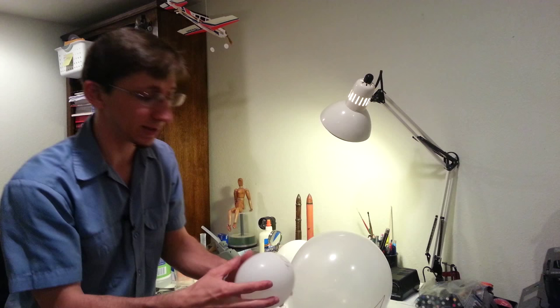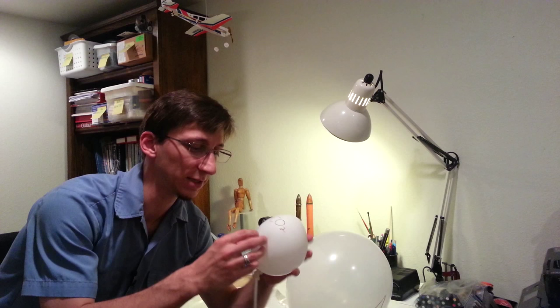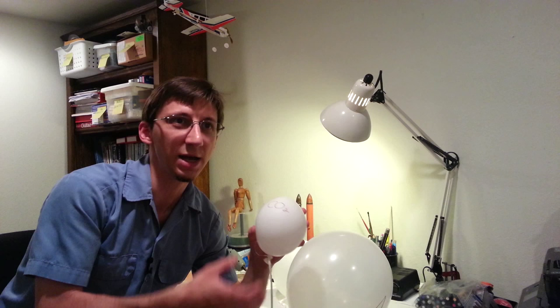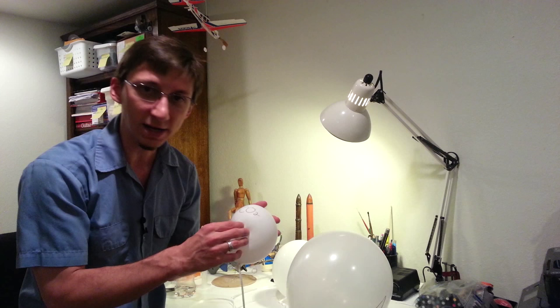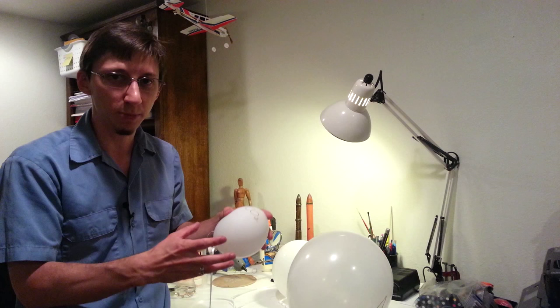Case in point, carbon dioxide. Carbon dioxide was the largest molecule we had, and yet it shrunk the fastest. Apparently, carbon dioxide dissolves into latex. Like, if you had liquid latex, you'd be able to dissolve a lot of carbon dioxide into it, and that property continues even when the latex is solid. Sort of the carbon dioxide almost worms its way in, so it deflates much faster than the rest of them. I mean, this one deflated within 8 hours.